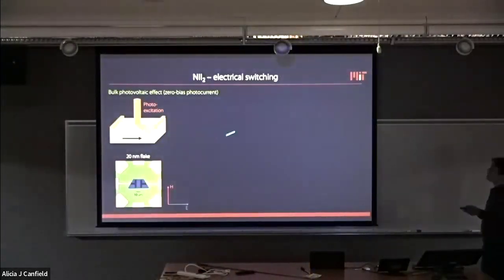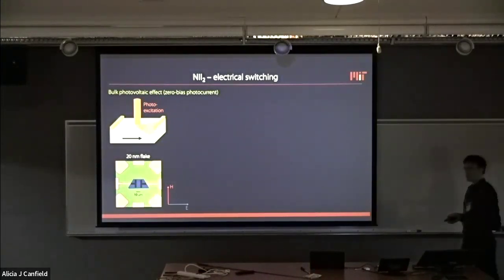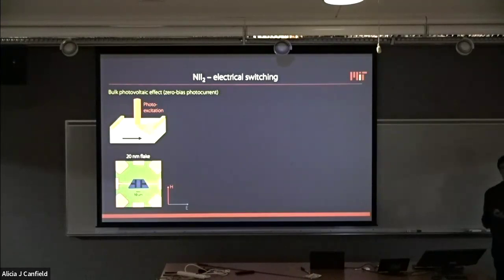And then electrical switching. In the ultra thin limit it is very challenging to measure pyroelectric currents. They are below attoamp levels because of the very small sample volume. So it's extremely challenging, and one solution is to use a photocurrent type of approach. We photoexcite carriers across the bandgap in this case, and then we look at a photocurrent at zero bias. So we're not biasing across the contacts; we let the internal electric field of the sample drive the photocarriers one way or the other.